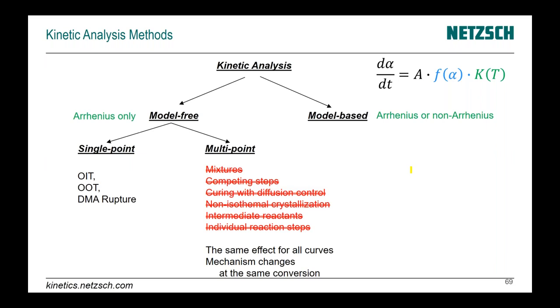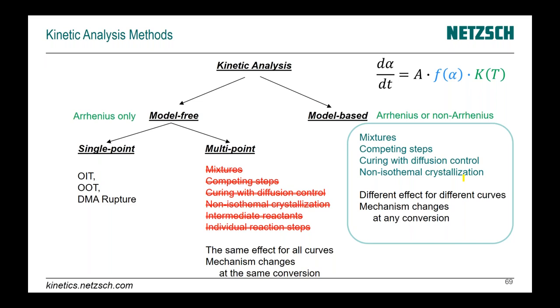To summarize: model-free analysis has single-point and multipoint options, but is not suitable for mixtures, competing steps, diffusion control, or non-isothermal crystallization. Model-based analysis works for mixtures, competing steps, curing with diffusion control, and non-isothermal crystallization. All these things are written in the ICTAC Kinetics Committee recommendations for multi-step kinetics. If you would like to get additional information, you can find it there.